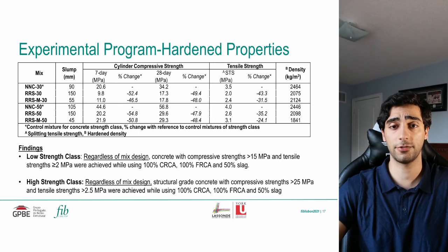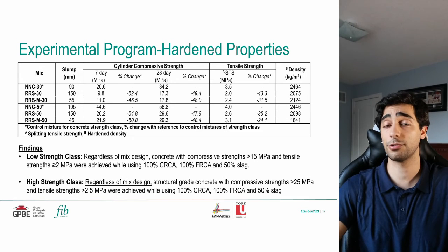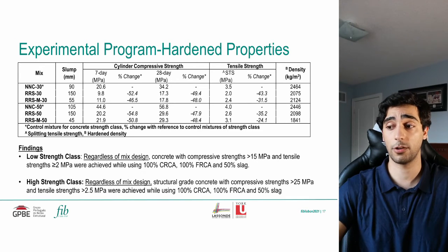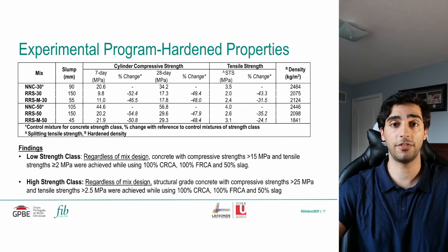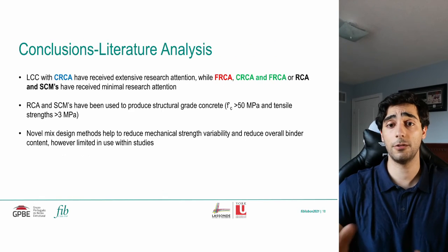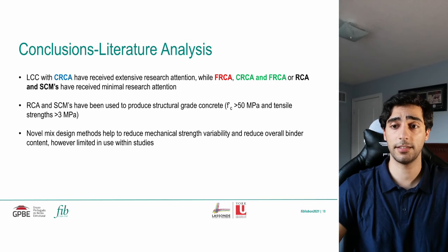In summary of the experimental findings, the low strength class, regardless of the mixture design method, were able to achieve compressive strengths of over 15 MPa and tensile strengths over 2 MPa while using 100% coarse, 100% fine RCA and 50% slag, while for the high strength mixtures, regardless of mixture design, structural grade concrete with compressive strengths over 25 MPa and tensile strengths over 2.5 MPa were achieved while using 100% coarse and 100% fine RCA and 50% slag.